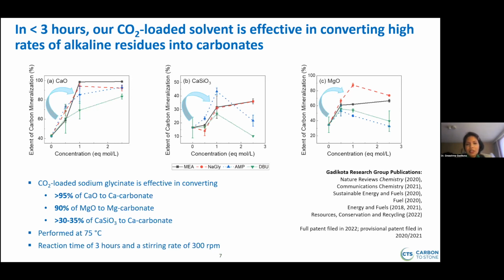So sodium glycinate is environmentally benign. It has similar CO2 capture efficiencies as MEA. It's less corrosive and it's more environmentally benign than MEA. So if you look at calcium silicate, for example, there's a lot of calcium silicate in alkaline residues, by the way, particularly slags. You'll see that we're able to get extensive carbon mineralization of about 30%. Which is actually very, very attractive because the process takes place at 50 or 75 degrees centigrade with 1 molar sodium glycinate. And this is, again, not using very high temperatures or very high pressures.